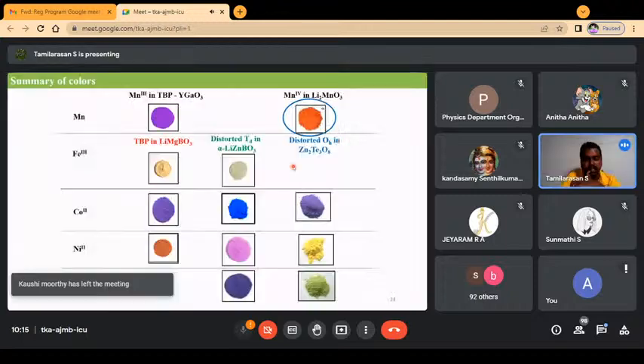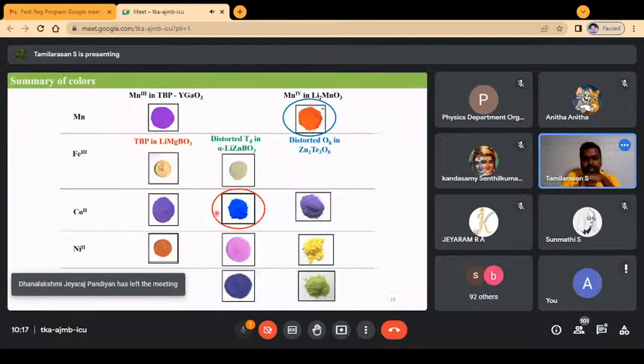So during my PhD studies, these are different colored materials we formed. Fortunately, we could characterize this red color, which is very rare in nature to find. Usually red colored materials contain toxic elements like mercury. So we said that this is a non-toxic red colored material, and also we made this compound with very bright blue color, brighter than the classical cobalt spinel.